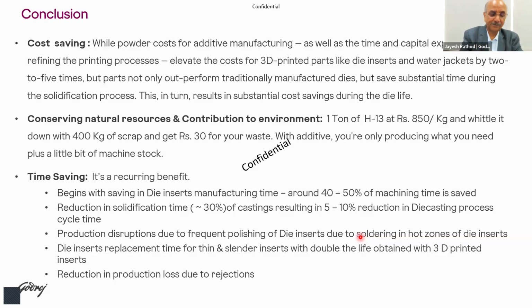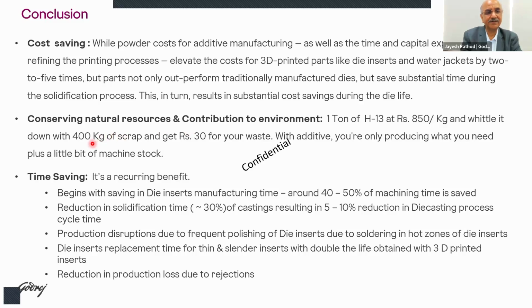Another aspect we should be mindful of is that we are conserving natural resources and contributing to the environment, because this is an example of a 1 ton H13 block. In the conventional way, the rate would be in the range of 850 rupees per kg. We are removing around 400 kg of material just to get the profile. That 400 kg of scrap will then be sold at 30 rupees per kg as waste.